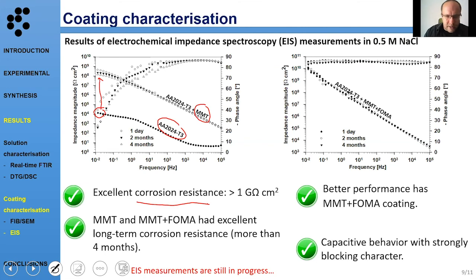But on the other hand, if the coating contains also perfluoro molecules, these values are even higher, and it remains much more stable during, for example, 4 months immersion in sodium chloride solution. So that means that by modifying this coating, we can also tailor it and get better corrosion resistance if this alloy is coated with this kind of coating.